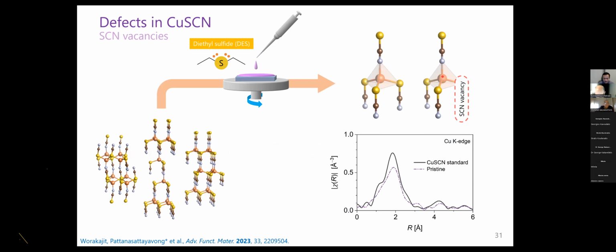And we also did the analysis of X-ray absorption spectroscopy from synchrotron-based experiments again. We see that, compared to the bulk powder sample of copper thiocyanate from direct synthesis, and the copper thiocyanate after processing with diethylsulfide, drop cast into powder sample, and then annealed to try to get rid of some of the solvent molecules already, when we look at this one here, we are observing X-ray absorption near the copper K-edge. This gives information about the local structure around copper. So we see that the structure around the copper atoms becomes less ordered, so more disordered.